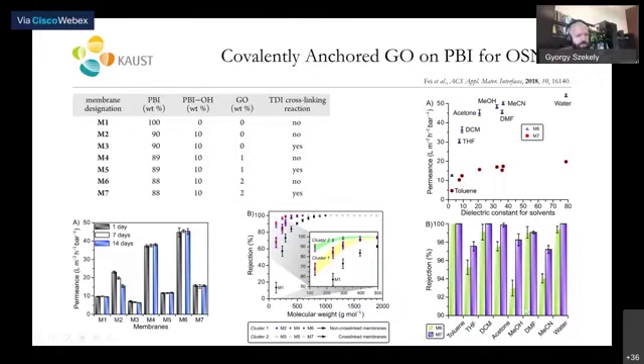And here we observed something unexpected. So if you look at this data set, then all of these solvents are fine with the cross-link membranes, but the non-cross-link membranes usually are not stable in polar aprotic solvents. And here you can see DMF, which is a polar aprotic solvent, and nonetheless, the non-cross-link membrane, the green one, was also stable and showed more or less similar rejection profile as the GO-incorporated cross-link membrane.